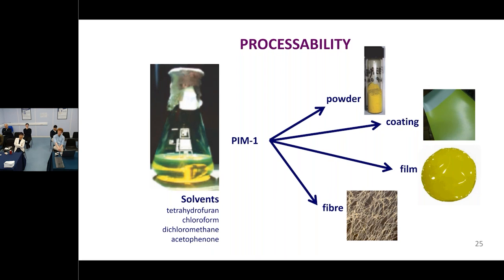And what you have in the end is a glassy polymer. We never see it in the rubbery state because we can get up to 350, 400 degrees C, and eventually, being a polymer, it can degrade. There are ways now of catching the glass transition just by having a very, very rapid jump. But we never see it in the rubbery state. It's always a glassy polymer in practice. But we can make it into coatings and films, and it has many of the properties of something like an activated carbon, but it's processable in a way that something like an activated carbon is not.